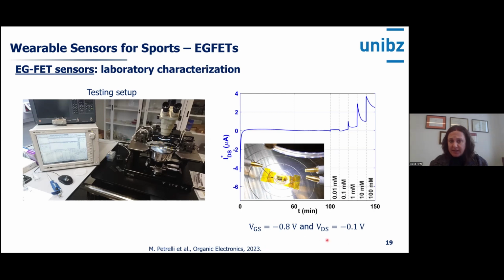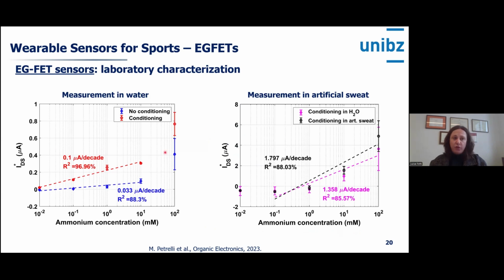Being an electrolyte-gated transistor, we work at very low voltages, and that's one of the advantages also. So it's a very low power technology. This is the interesting process window of the devices, what we're interested in for these applications. And you see also the calibration curves of the devices, first in DI water, but also in artificial sweat, especially when we have conditioning of the devices, which is very important, the membrane conditioning. So pretty linear behavior with good sensitivity and good linearity.